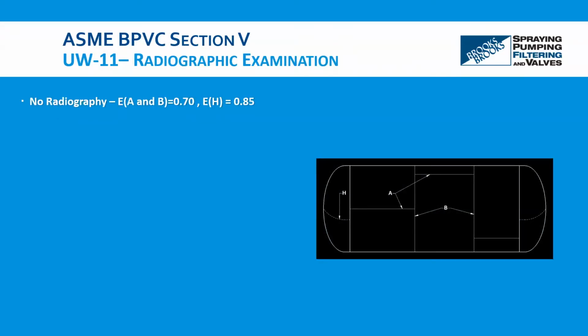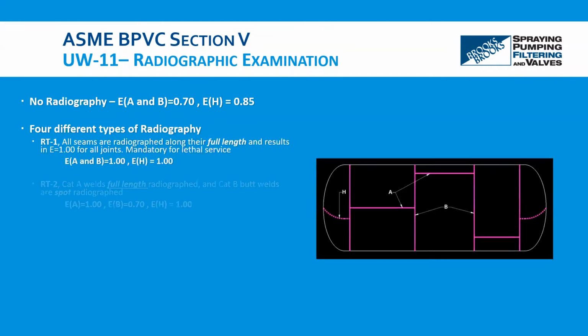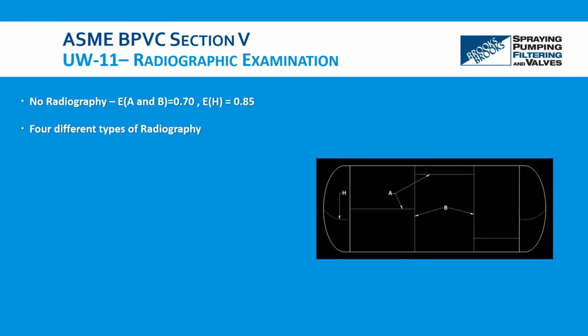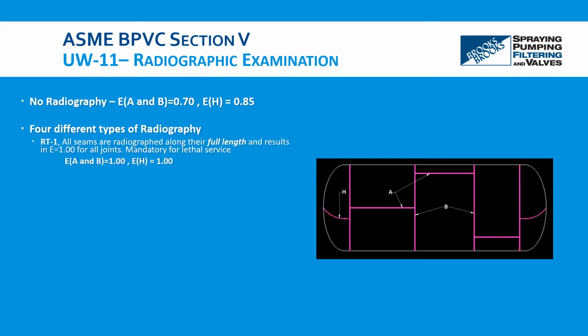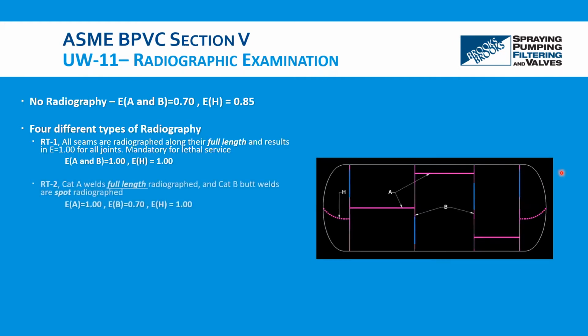Now, what effect does this radiography have on joint efficiencies? We mentioned it earlier, and here are a couple instances where you can see where the radiograph is done and what that does to the joint efficiency. So for full radiography or RT1, you have a joint efficiency of 1. In other words, 100% joint efficiency.